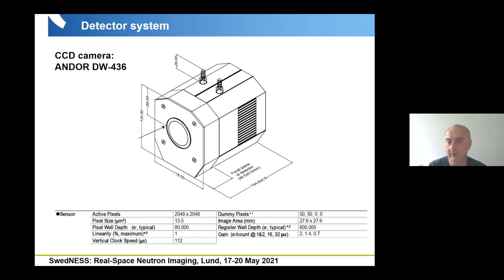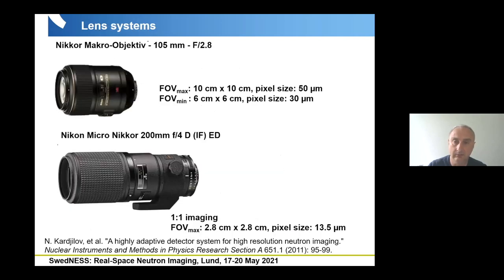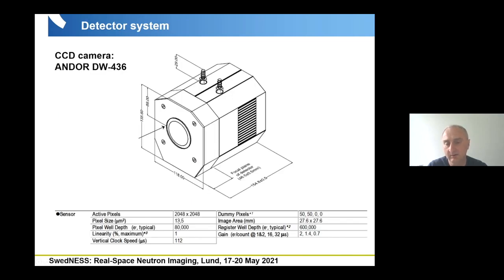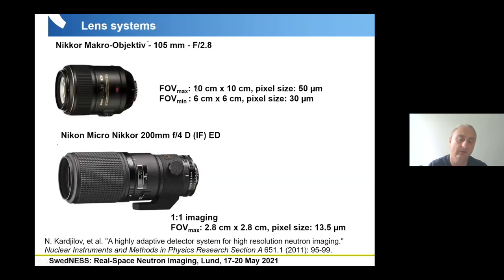Such cameras cost more than, let's say, 20,000 euro. So it's very delicate equipment. For these digital cameras, we are using some commercially available lenses where we can change the effective pixel size. You can see here that the pixel size provided by the chip of the camera is about 13.5 micrometers. There are different types of cameras, but by using different lenses, you can zoom in or zoom out on the scintillator, and then you have effective pixel sizes of 30, 50, and more than this micrometers.